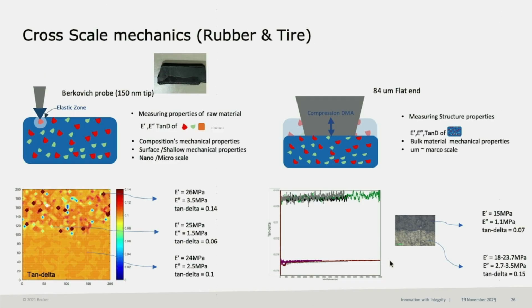So we use high-speed indentation. You can see there is a clear boundary of the interface. The upper rubber has some particle mix. This can be detected by our nano indentation with high-speed mapping, because we use a very sharp tip to do all the indentation in a very localized position. If we are using the DMA, you can get the E prime, E double prime, tan delta. Each phase has different mechanical properties here.